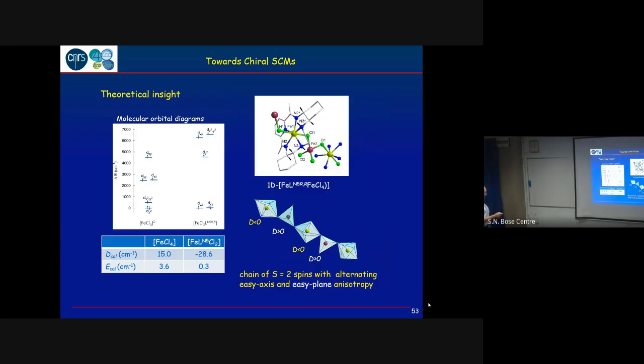Just a comment: here we have a chain where we alternate negative and positive anisotropy, and this is a homometallic chain, an iron-only chain. DYZ and DXZ are not at the same energy, but they are very close in energy, with a very small gap. That's why you have very large anisotropy. Exactly. Because if now you send one of these electrons to this orbital or to this one, the energy gap here is huge. And the anisotropy is inversely proportional to this energy. So this means that it's mainly the negative contribution that comes in.